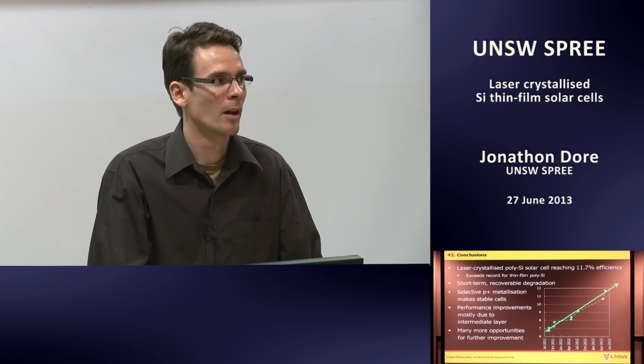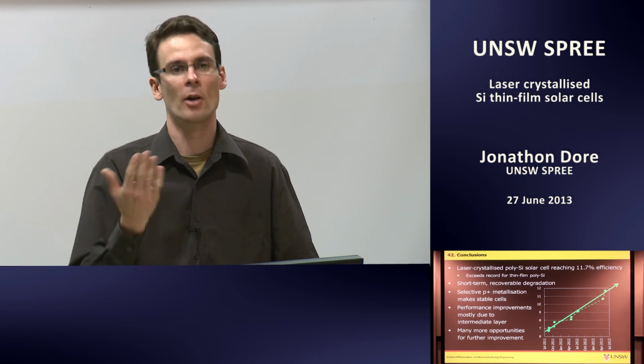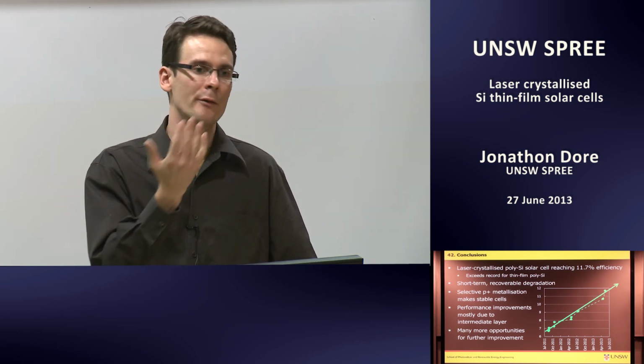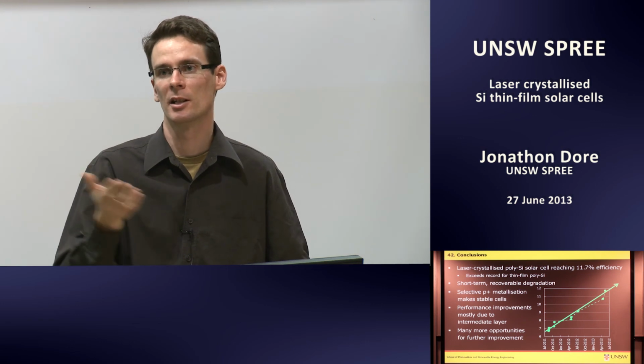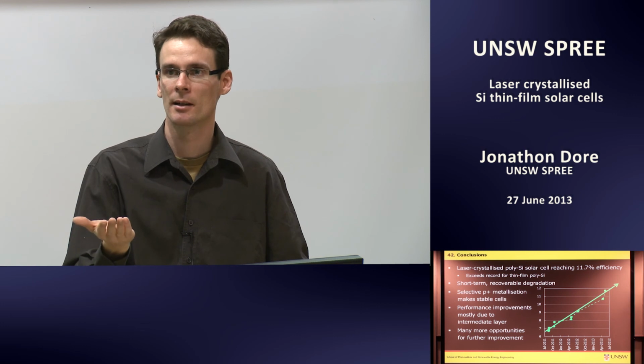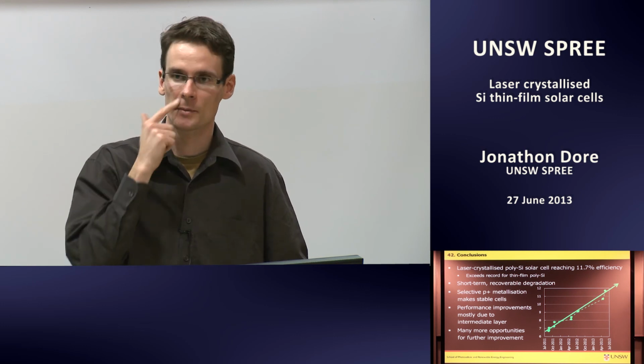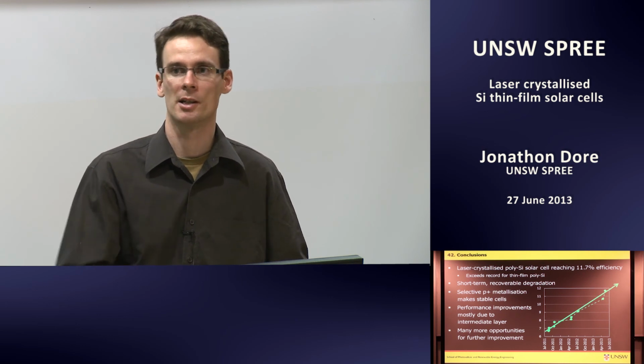We don't understand how it works. We're just trying faster, trying slower. That's it. More obviously, power, less power. You have effects there with the thermal expansion. You've got the silicon expanding, and you've got it going through phase transformations. You do have a bit of glass heating at the very surface. So all those things can occur, that can cause some stress and some cracks to open up.